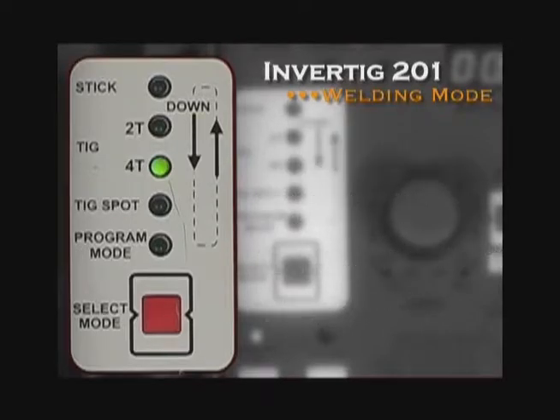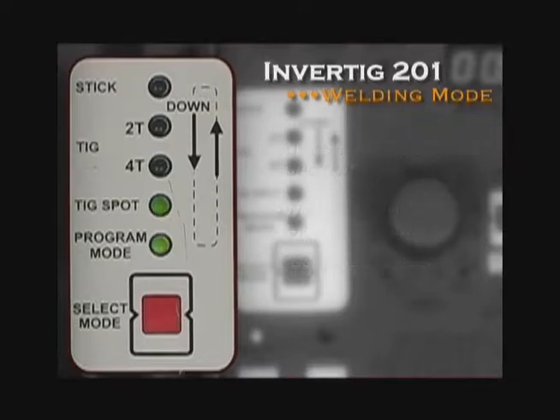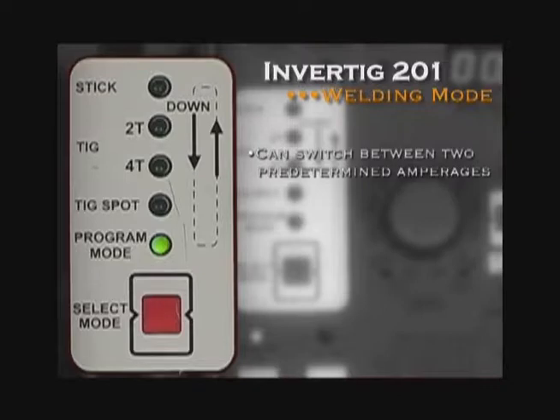The TIG spot is for repetitive TIG spot welds. The machine will weld from 1/10 of a second to 10 seconds. This is set by adjusting the spot weld time. The program mode will allow you to switch between two predetermined amperages and is again used with the momentary contact switch.